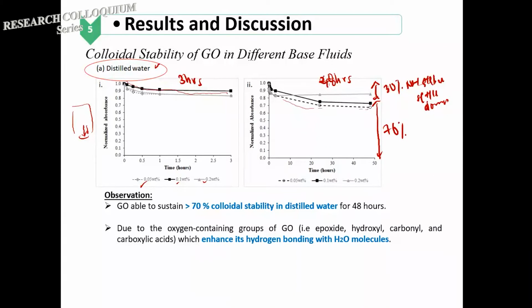Now, this could be due to the oxygen-containing group of the graphene oxide. Because the graphene oxide itself already has the oxygen-containing group, it's definitely able to form hydrogen bonds with the H2O molecule. That's the reason why it has good colloidal stability inside the distilled water itself.